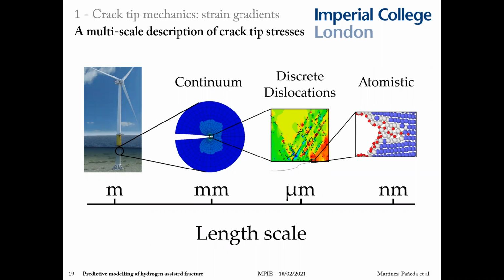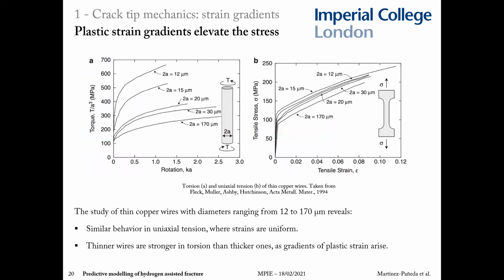That means we introduce the physics implicitly, so to say, by changing your constitutive equations. So you can compare what your continuum model predicts at a micron ahead of the crack tip with what discrete dislocations predict, for example, and then when you see the difference, you can enrich your continuum model. And the main effect that you're missing at 1 micron ahead of the crack tip is the dislocation hardening mechanisms associated with plastic strain gradients.